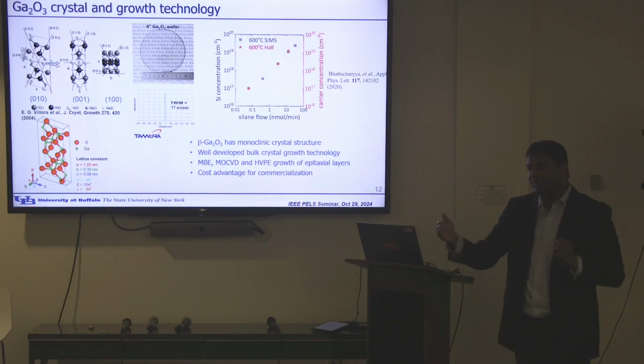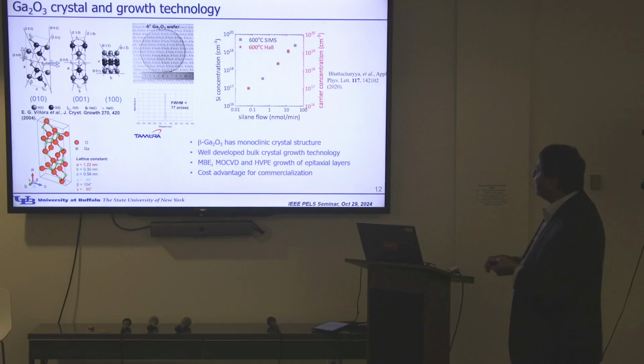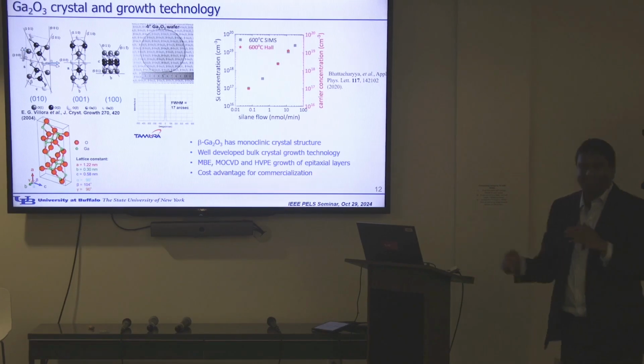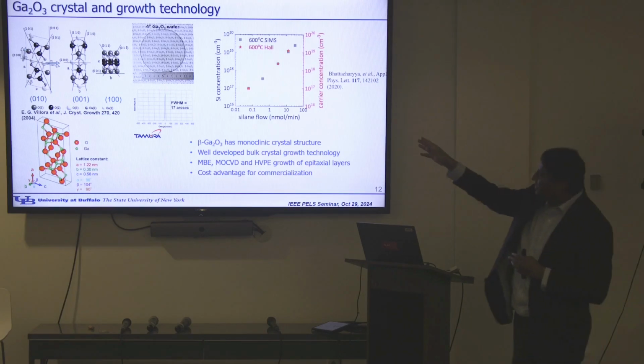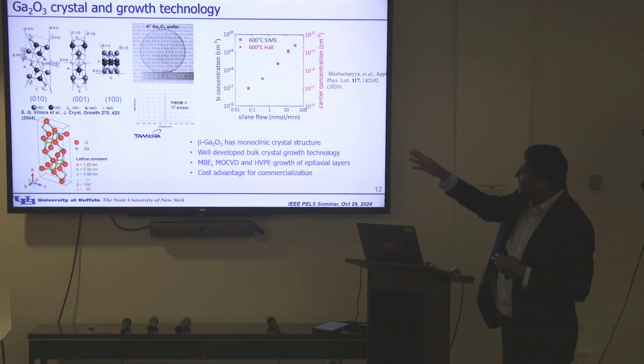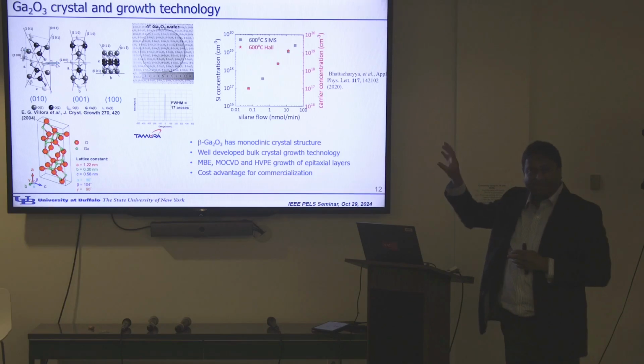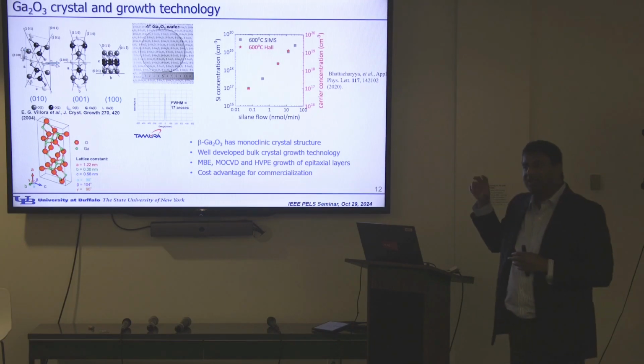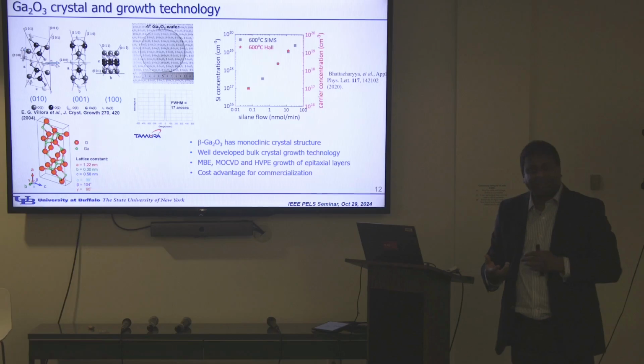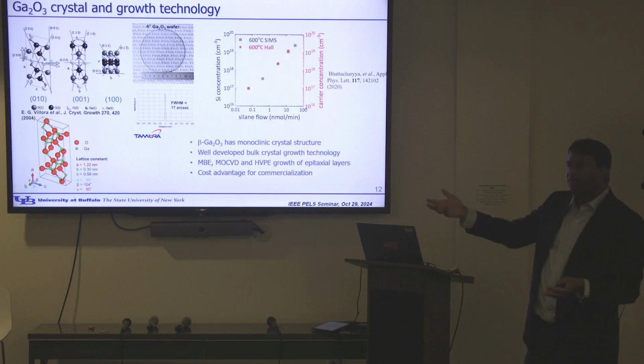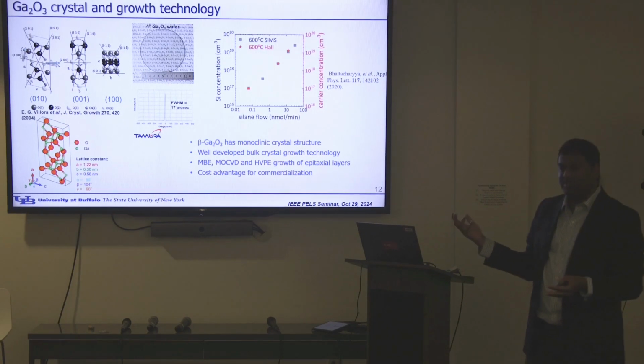So if you look at mobility, in all directions it's almost the same, right? So you just don't have to worry about that. Luckily, otherwise the modeling gets a little bit more complex. And you see in the center here, it's a 4-inch substrate, and that's actually unique for gallium oxide compared to other semiconductors, where substrate technology was always lagging behind epitaxial layer, right? So here, the substrate was mature before people started doing the device fabrication, right?